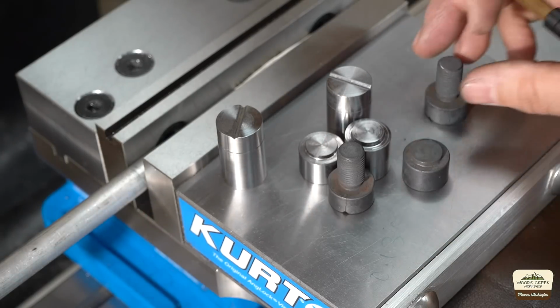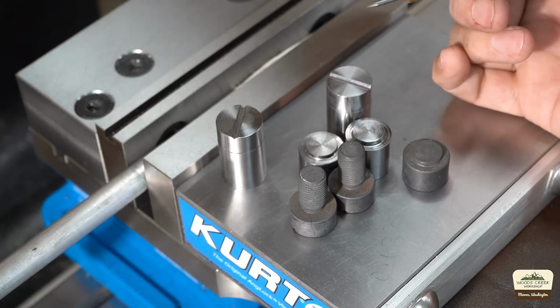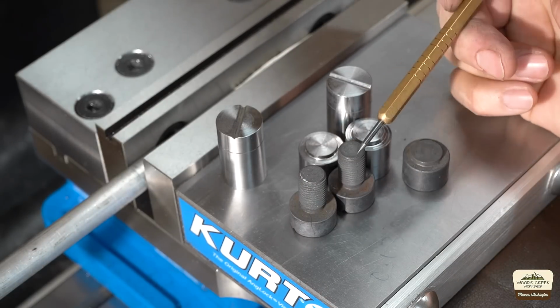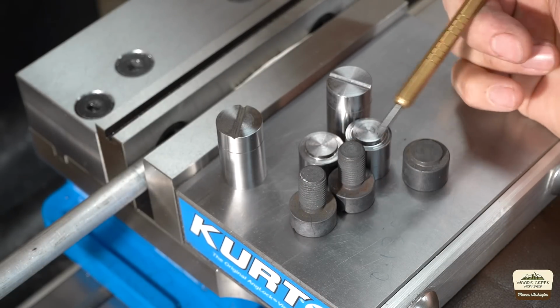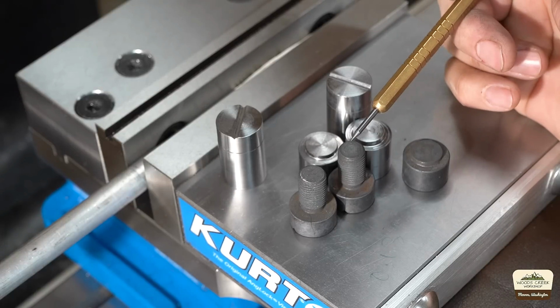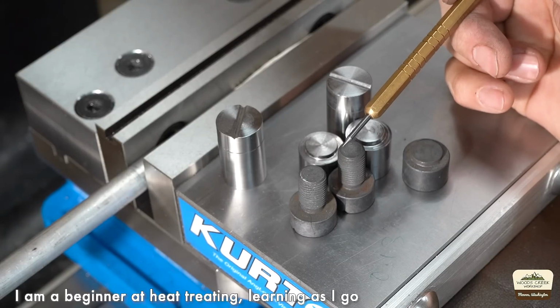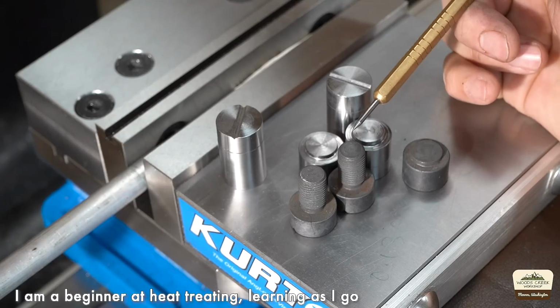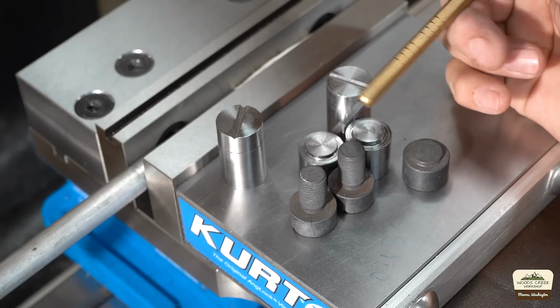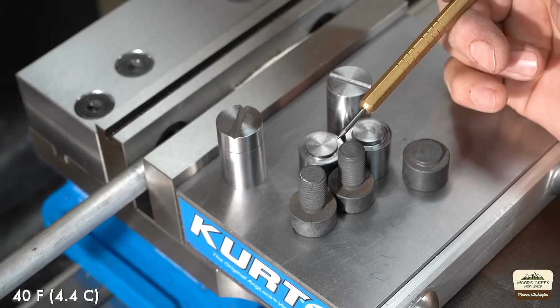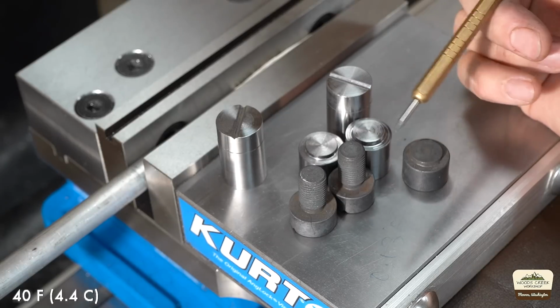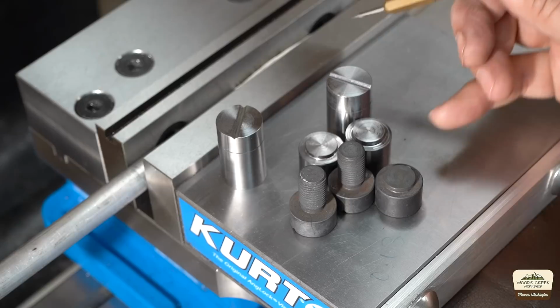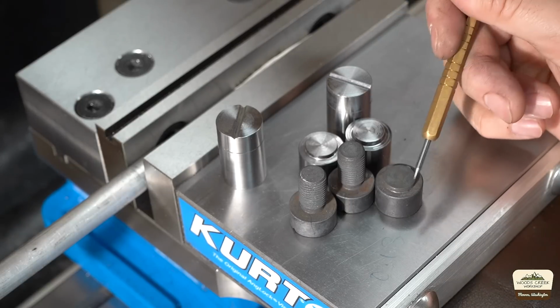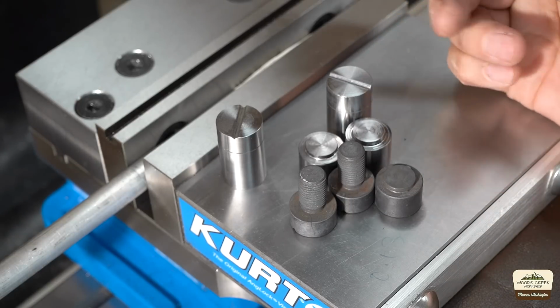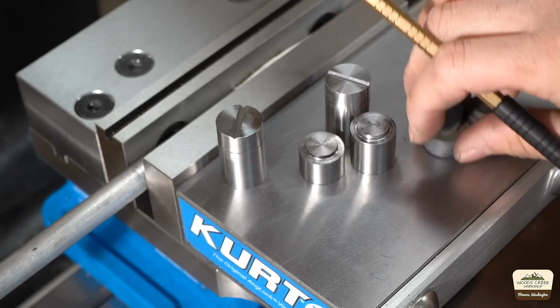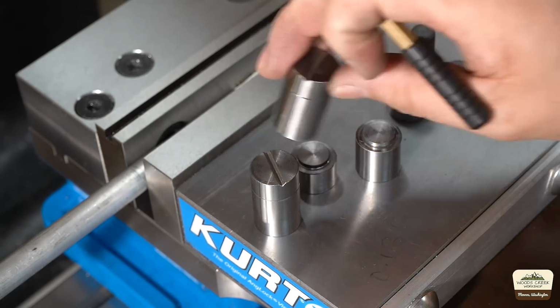And this is what happens when I don't pay attention to the quenching. These are W1 steel, so you're supposed to quench in water. And I didn't pay attention. I didn't even think about the temperature of the water. It was a little chilly, so it was probably around 40 degrees Fahrenheit. And it just proved to be too drastic, too much of a shock. And these just cracked. So obviously I made new ones.